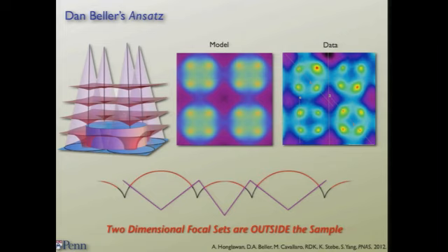So we use AFM to measure the height of the surface. Here are the cones. So here's a pair of purple cones. They're pointing in a little bit. And here's his surface. So here is the focal conic domain part, the black part, and he connects them with pieces, arcs of circles. He minimizes the energy. The energy is reasonably lower.